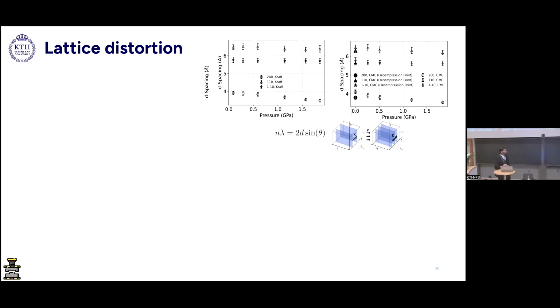Now we wanted to see how the lattice is getting distorted, so we calculated the d-values, the lattice spacing, for the different crystalline peaks. We could see that all of the crystalline peaks, the three that we could recover, the 1-10, 110, and 200 peaks, showed a decreasing trend. That basically means we are pushing the lattice planes together, as demonstrated here. This was also seen in the dried cellulose case in the literature, so we were working our methodology off of that.